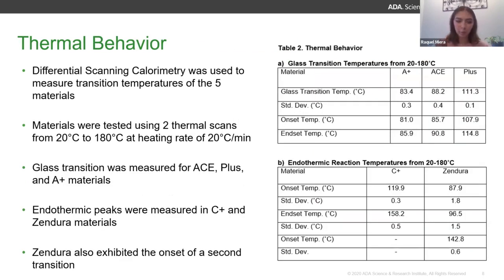We also tested thermal behavior. We used differential scanning calorimetry to measure transition temperatures in all 5 materials. We used 2 thermal scans from 20 degrees Celsius to 180 degrees Celsius with a heating rate of 20 degrees Celsius per minute. And we were able to measure the glass transition in ACE, Plus, and A+ materials.